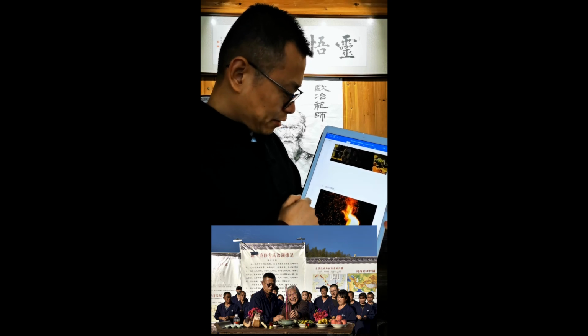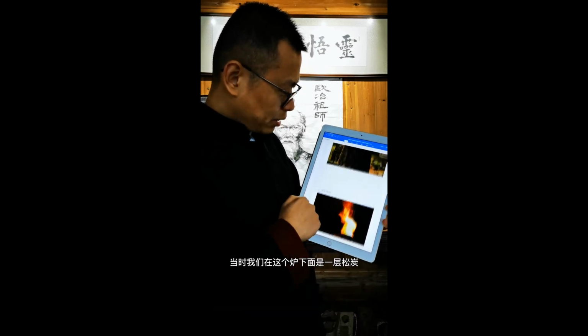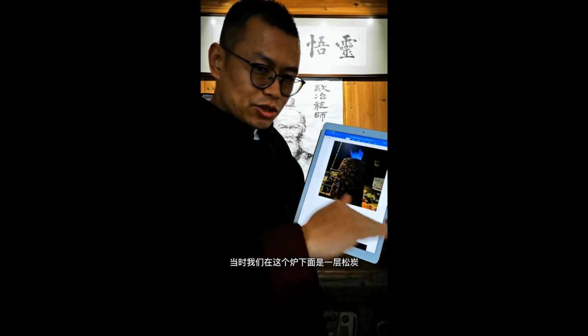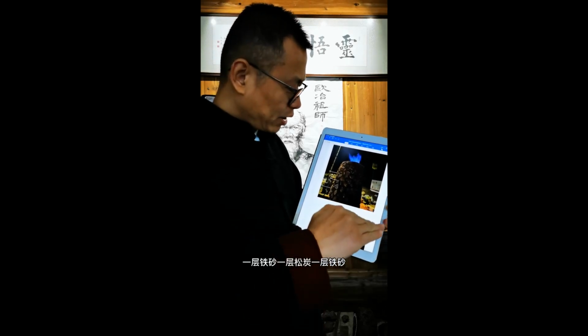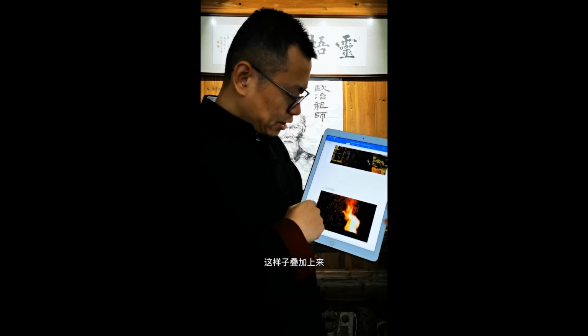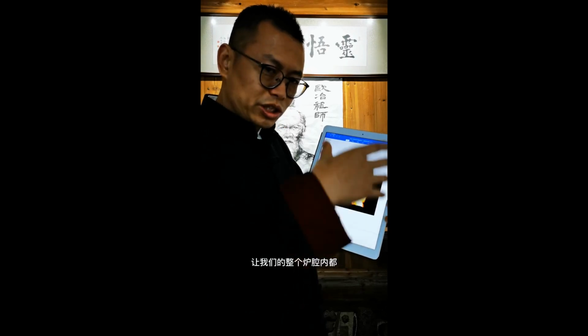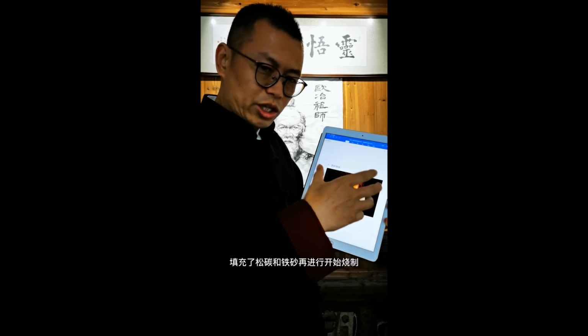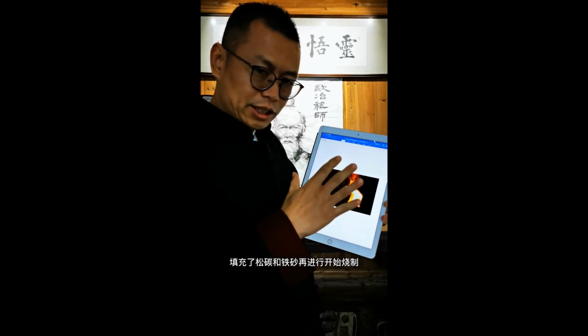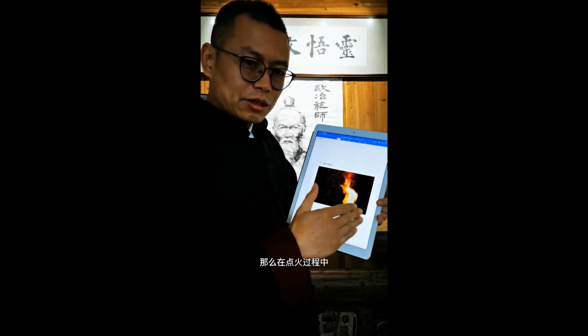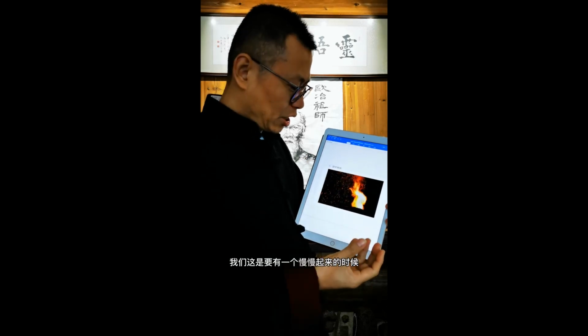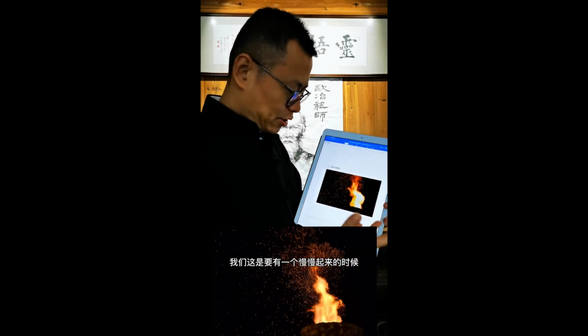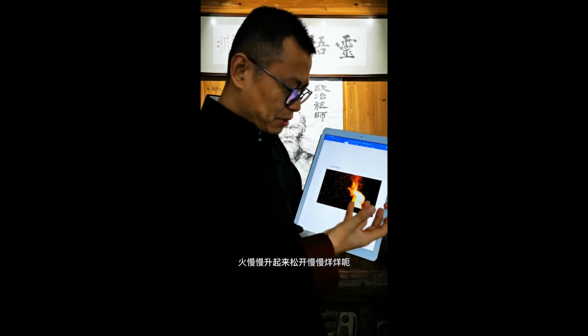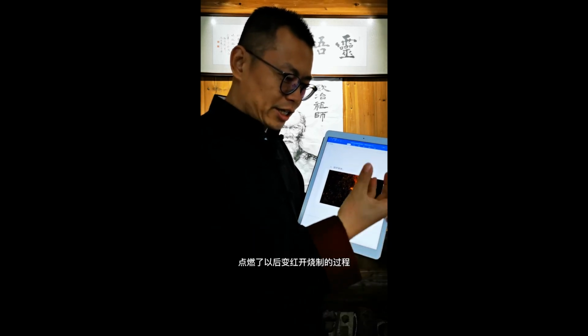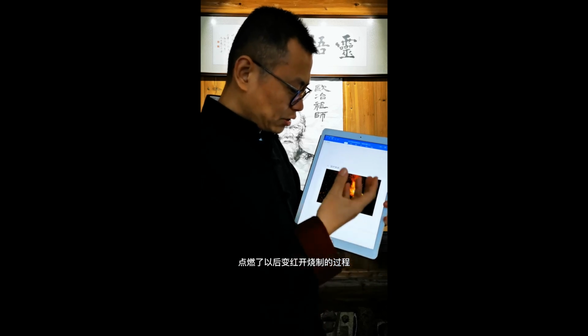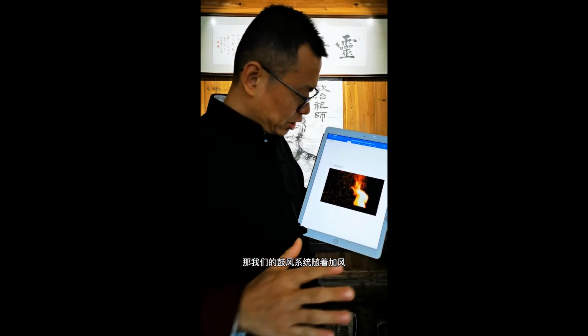And step 5, we start the melting process. At that time, we put one layer of charcoal, another layer of iron sand, and then another layer of charcoal, followed by iron sand. The whole furnace cavity is filled with charcoal and iron sand. After the ignition, the charcoal became red and got molten, and then the smelting began.